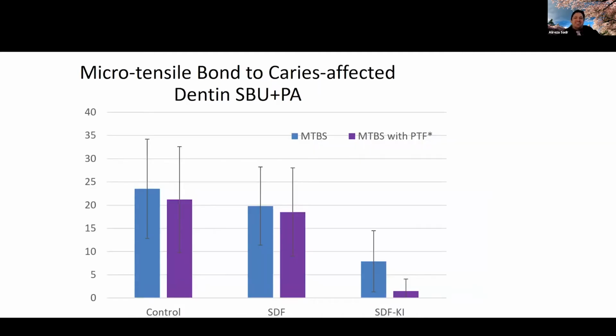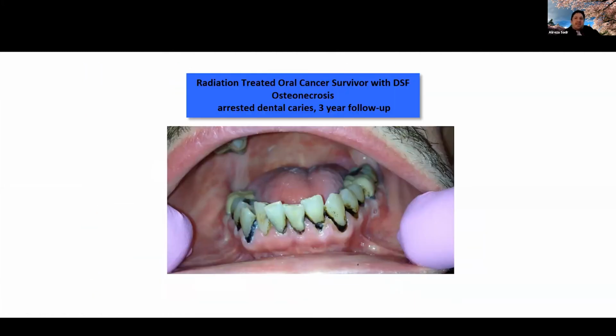Okay, so you see here the bond strength to SDF KI treated dentin, even with phosphoric acid etching, was not great. It was very good with the SDF only after the phosphoric acid etch, but we didn't get good enough bonding with potassium iodide treated dentin.